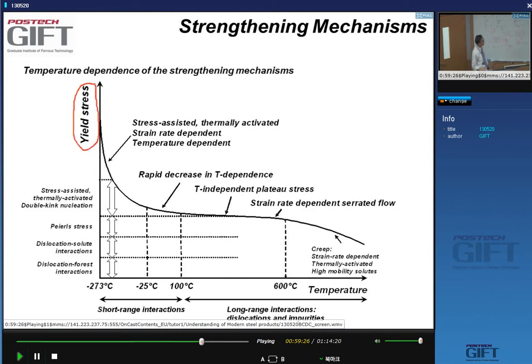the yield strength of a steel is temperature dependent. The dependence looks like this: at very high temperatures I get low strength, and then a plateau where the strength is temperature independent, and then around room temperature, if I decrease the temperature, I get a rapid increase in the temperature dependence. Now, the level of this strength here depends on,